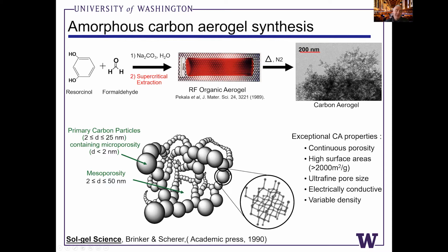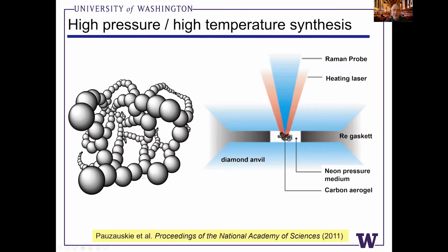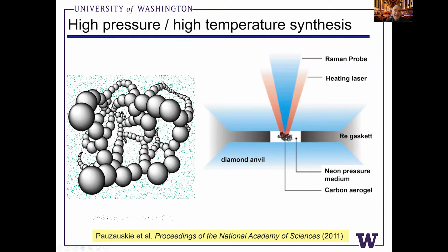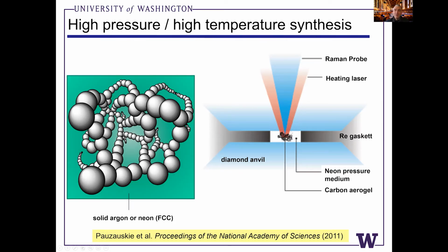But the idea is we can take this high surface area nanoscale amorphous carbon sphere and try to convert it into a nanodiamond structure within the diamond anvil cell. So the first step is we load the carbon aerogel into the diamond anvil cell. We use cryogenic liquid noble gases. This is either argon or neon so far, but we're very interested in moving on to working with xenon for reasons I'll discuss later. But we can effectively fill the pores of the aerogel with a liquid noble gas. We can then compress the noble gas and freeze it at high pressure at about 1.8 gigapascals.